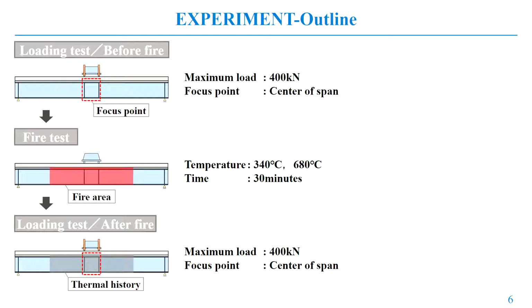This figure shows the flow of the experiments. First, a static loading test was carried out at room temperature to confirm the behavior of the composite girder. Next, the fire test was carried out and the temperature distribution of the composite girder was measured. Finally, the static loading test was repeated.